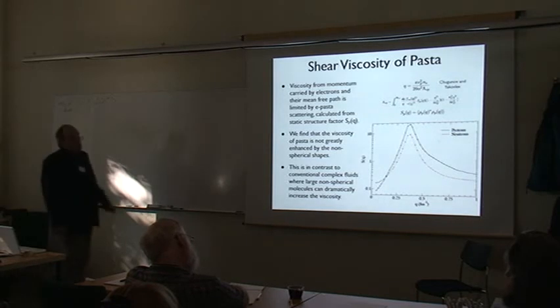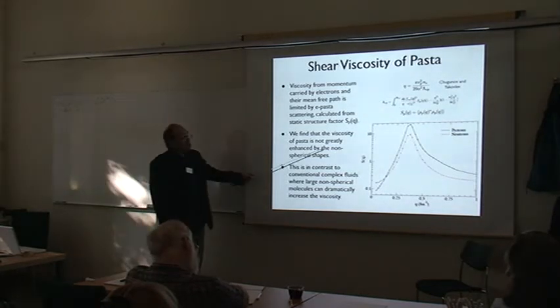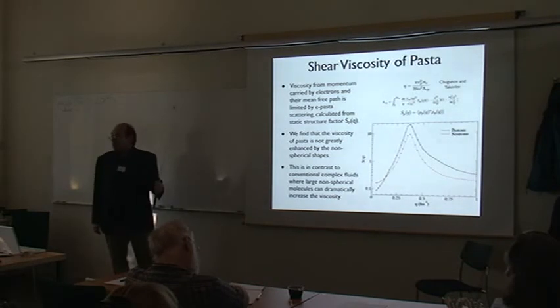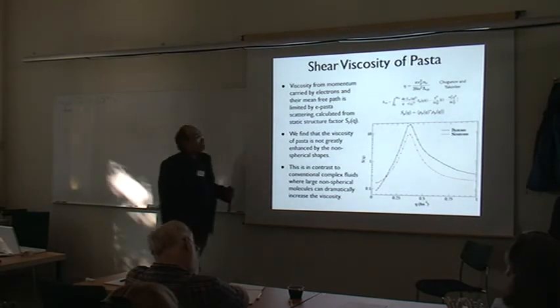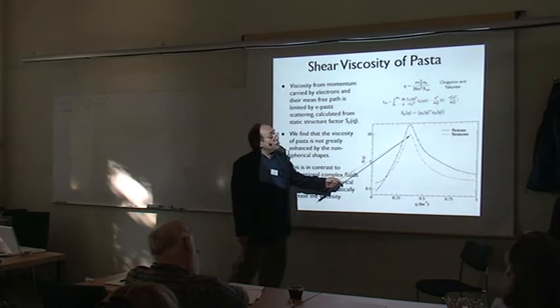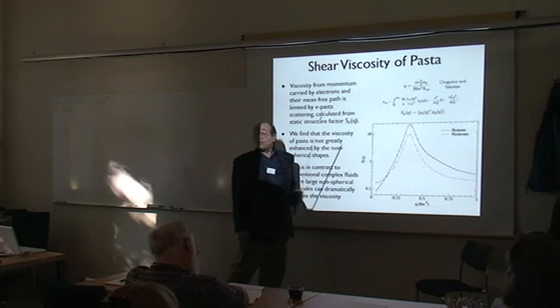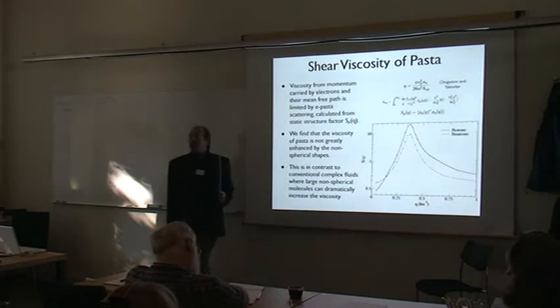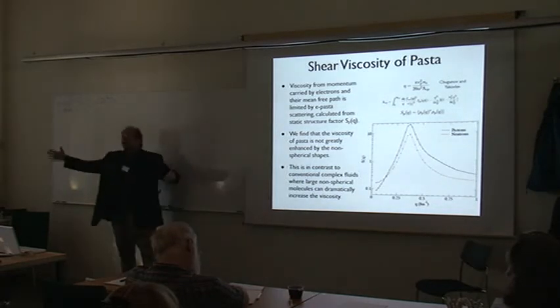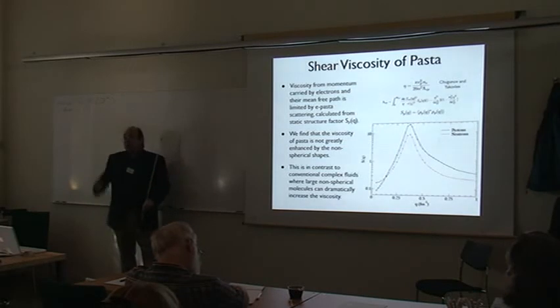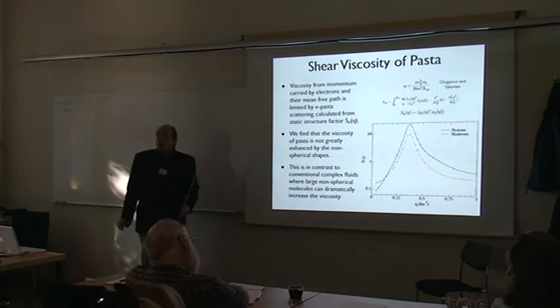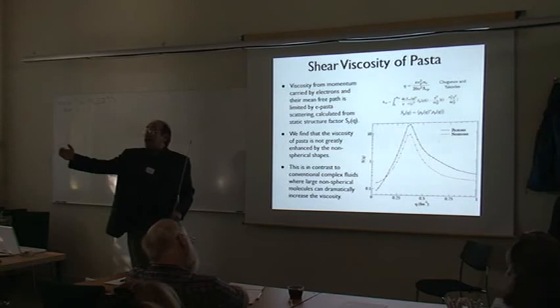And you're actually scattering from density contrast—there's a lot more neutrons in the system than protons. But the effective number of neutrons, this peak S of Q for the neutrons, is actually smaller than that for the protons. The reason is that the pasta sauce, all the neutrons outside the pieces of pasta, reduce the contrast.